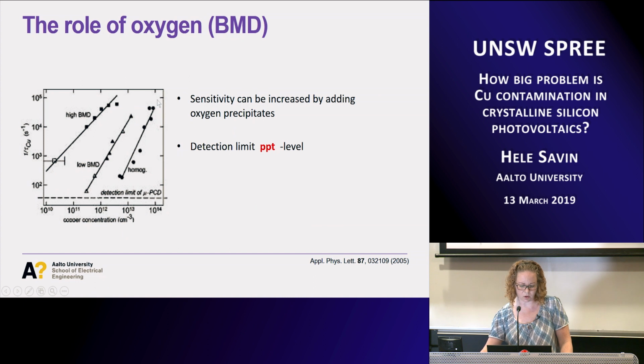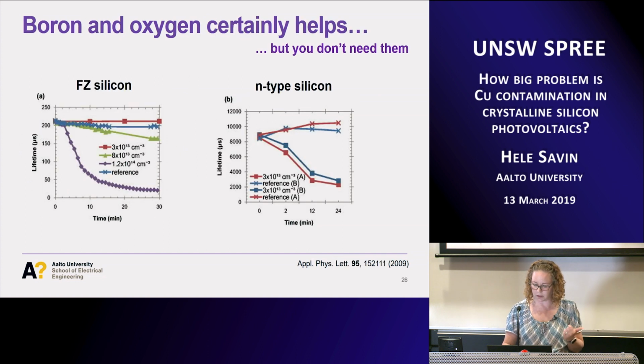So if we have no oxygen, our detection limit is somewhere around 10 to 12. If we add oxygen to our wafers, with the same amount of copper we have much stronger LID, and if you have the highest amount of oxygen precipitates, then, of course we need to extrapolate, but we can basically go to really low concentrations and have a parts per trillion level resolution. So oxygen definitely helps this copper LID reaction.